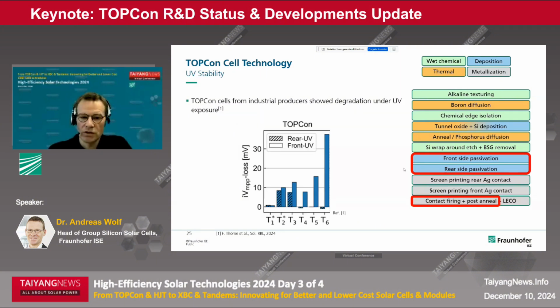Looking at the passivation, we saw that UV degradation is currently a hot topic. There's a recent publication from ISE where we investigated cells from industrial producers and also observed some severe UV instabilities for the cells, meaning that these were investigated without any cover glass or encapsulant, but the cells themselves showed quite strong degradation. This is something that should be investigated in more detail and should be carefully monitored.